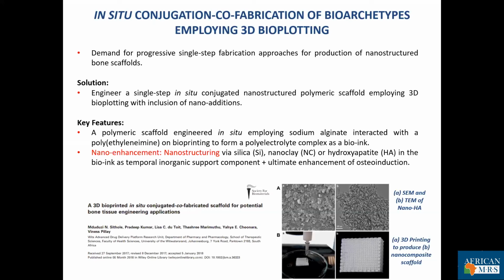Another approach which we looked at was essentially a one-step approach, an in situ conjugation co-fabrication approach, also employing here 3D bioplotting for a nanostructured bone scaffold. So the inclusion of the nano additions here was your nanostructuring by your silica, nanoclay, or hydroxyapatite. And this was then used as a bioink.